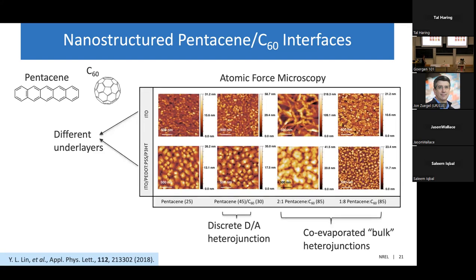We created what's called a discrete donor-acceptor heterojunction, where you deposit pentacene, then you sequentially deposit C60, and you essentially have a planar heterojunction between the 2 materials, as well as what's called co-evaporated bulk heterojunctions, where your molecules are evaporated at different ratios together. So you get a nice mixture of the 2. And from the atomic force microscopy images, you can see that there's quite a range of morphologies being produced through these different methods.